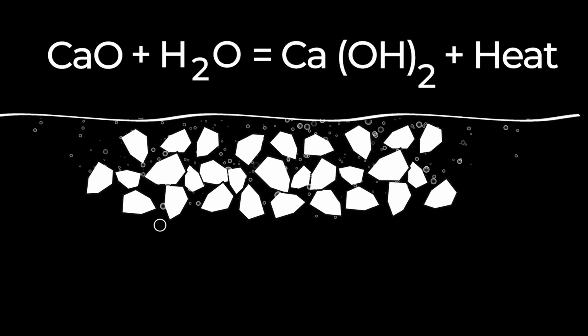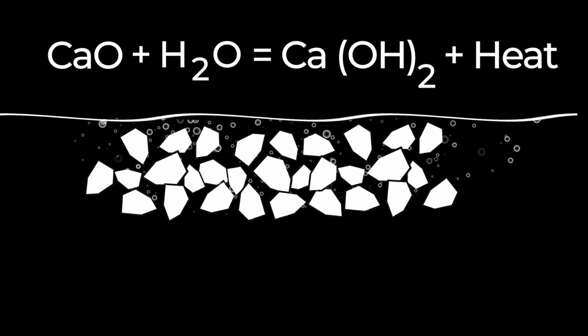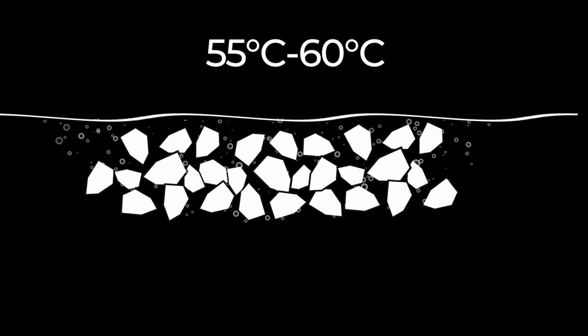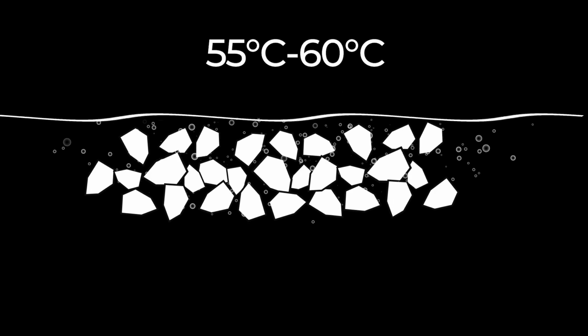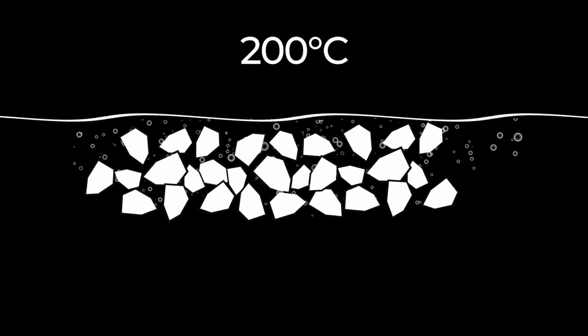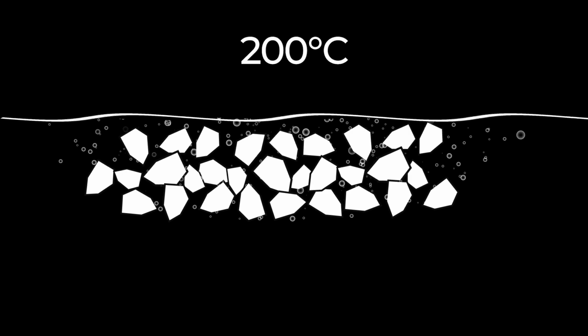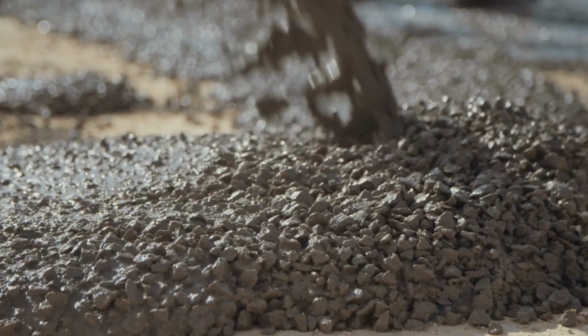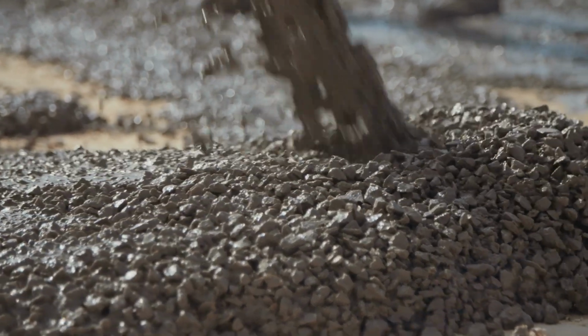The temperature increase in the mortar could be as much as 55 to 60 degrees centigrade over ambient conditions, with the presence of hotspots exceeding 200 degrees centigrade. The benefit of hot mixing would also be that this increased temperature significantly reduces curing and setting time, since all the reactions are accelerated, allowing for a much faster construction process.